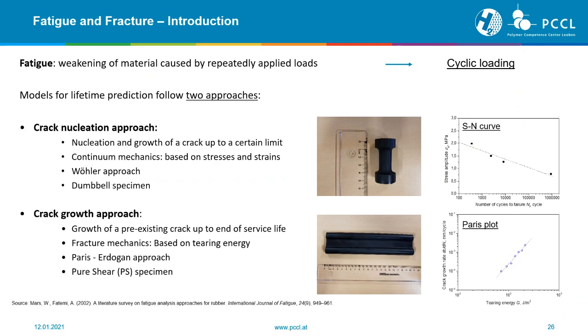What is fatigue? Basically, fatigue describes the weakening of the material caused by repeatedly applied loads, so-called cyclic loading. This means we just apply a cyclic load to our material. And here we can distinguish between 2 approaches. So we have the crack nucleation approach, which is based on sample specimens and a Wöhler approach. This means I define a stress amplitude, apply it to my sample specimen, and then end up with a number of cycles to failure. The second approach is the crack growth approach.